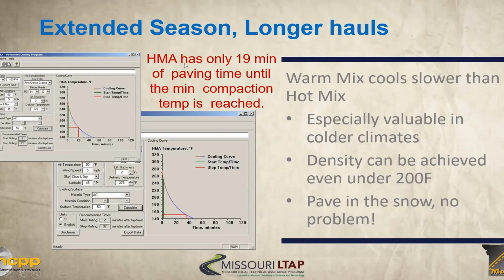And you can see that hot mix, especially this time of year, late season paving or early season paving, hot mix only has 19 minutes of paving until minimum compaction temp is reached. And then if you look down here for warm mix, you get a much longer time frame. So with warm mix, you're extending that time frame. You can, as much as double the amount of time that you have. Densities can even be achieved under 200 degrees.